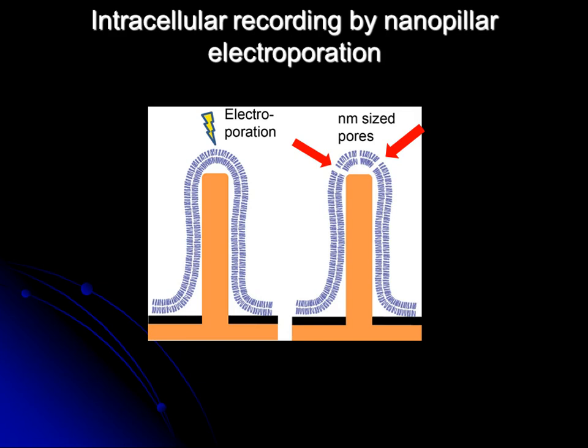It turns out our initial hypothesis is wrong. There is a membrane wrapping around the electrode, so the electrode does not directly access the cytosol as we initially hypothesized. That was rather disappointing. However, we realized that those electrodes are very sharp, about 100 to 200 nanometers in diameter. Instead of recording the action potential, we can also deliver an electrical pulse through the nanoelectrode. And by delivering an electrical pulse, those sharp nanoneedles will create a very high electric field gradient on the tip of the nanoelectrode.